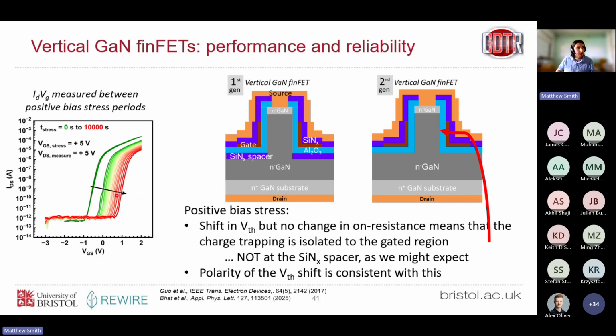If you want to have this kind of effect on the threshold voltage, what you need to do is trap charge in this region, so on these side walls of the fins underneath the gate. That's where we're going to get this threshold voltage shift.